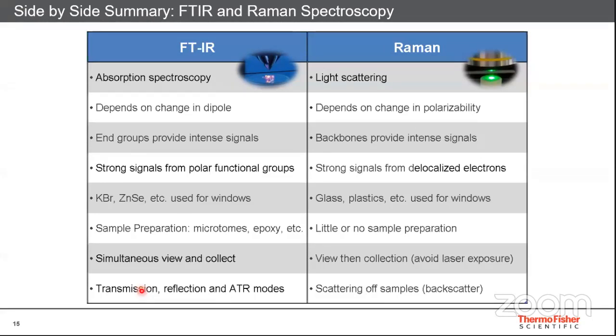So some sample preparation is needed in FTIR for some of the accessories, while in Raman, most of the time you need no sample preparation, or very little. The advantage of FTIR is that you can simultaneously view and collect. If you're working under a microscope, you can view the sample as well as collect the infrared spectrum. In Raman, however, you view the sample and then start collection, because the laser is harmful to your eyes. So whenever you're working with a Raman spectrophotometer, if it is an open system rather than a closed one, you have to use goggles for protection.